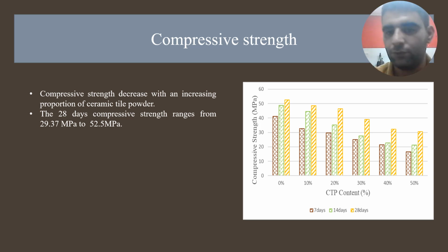This is mainly due to the dilution effect of cement and also the low pozzolanic reactivity of ceramic tile powder, due to the particle size being higher than the median particle size of the ceramic tile powder used in this study, higher than cement.